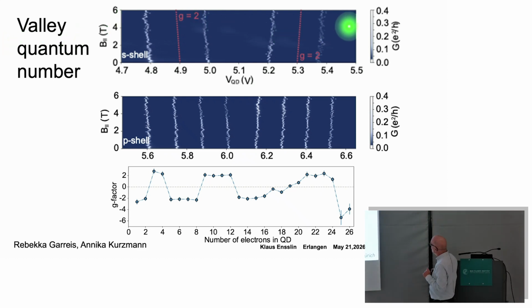Now, let's move on. That's the first 4 electrons. This is the next 8. And you see for the next 8, it looks the same. The first 4 move to the left, lower energy. They come in with the same spin, like Hund's rule in the periodic table. And then the next 4 come with the opposite spin. So if you plot these slopes in terms of a g factor, you see the first 4 electrons, spin down, spin up, the next 8 electrons, and then it gets a bit more complicated because obviously our single particle model that I've used so far doesn't hold anymore if you have 12 electrons or something like that in your quantum dot. But overall, you can understand how this spectrum looks in graphene, and it has an interesting twist to what we know in other systems. And that twist basically comes from the valley degree of freedom, which doesn't exist in other materials.